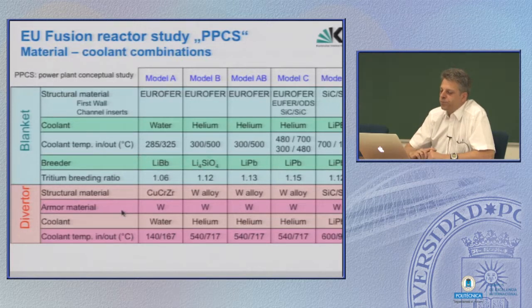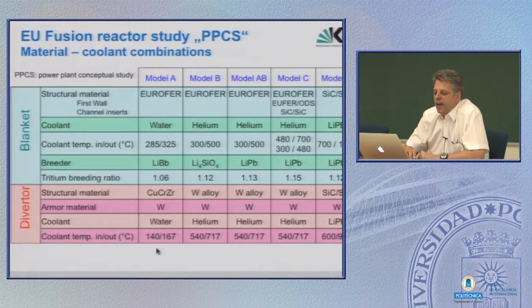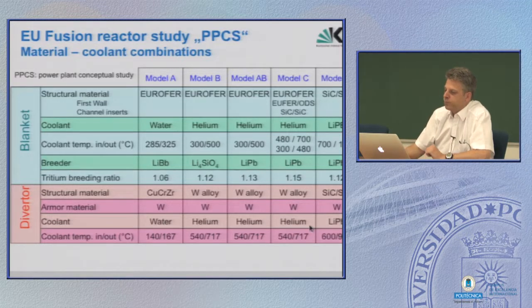In the divertor, it's relatively easy. There is a water-cooled concept like in ITER that is based on a copper alloy, copper chrome zirconium alloy. And within a certain area, not exactly what is written here in this concept, today we know more about it, but let's say in the range of 200 to 300 centigrade, this material could be safely operated. For all other divertor concepts, helium cooling is foreseen, and in the seminar I have already shown you the problems connected to tungsten. They are also immense because tungsten is so brittle even without irradiation. So I would say in general the divertor area is one of the biggest problems if we are talking about future nuclear fusion programs.